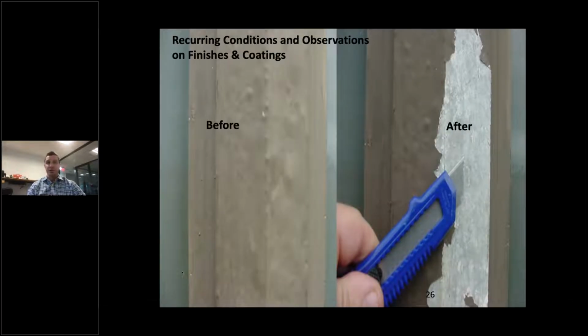And so when we investigated the building, we broke open some of the coatings that were there. The aluminum had been eaten away so much that the paint seemed like it was thicker than the aluminum on the building. And they asked us if we could repair it. We said, we cannot remediate this. The issue is far advanced from being able to be fixed. We recommended the entire curtain wall on the structure be replaced because the condition had been hidden for so long.